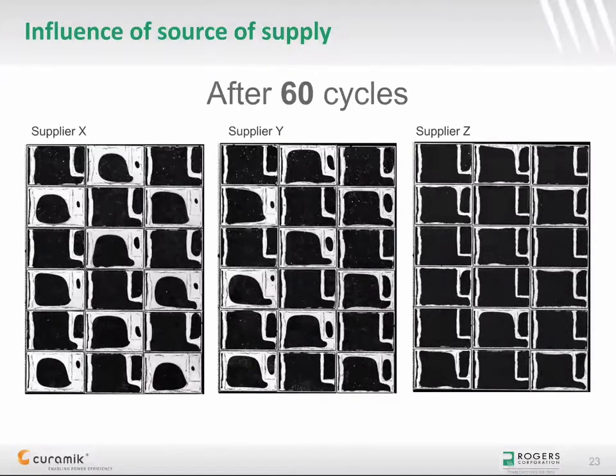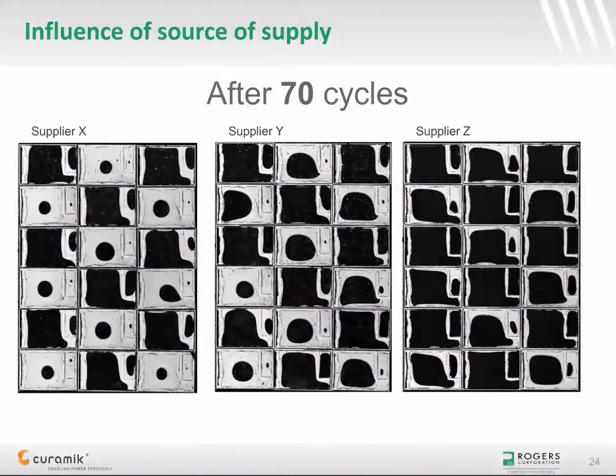In the scope of that study, we have also analyzed different ceramic suppliers. Here, after 60 cycles, the degradation of substrates with rounded corners is much more advanced than with sharp corners, irrespective of supplier. But the severe damages with supplier X cannot be observed for supplier Z. Same observation can be done after 70 cycles. The source of supply and quality of the ceramics has a tremendous influence on the reliability of substrates. To secure business continuity, multiple sources of supply are necessary. Rogers has been investigating many sources of supply and only qualified a few that deliver good and consistent quality to guarantee the best possible reliability.